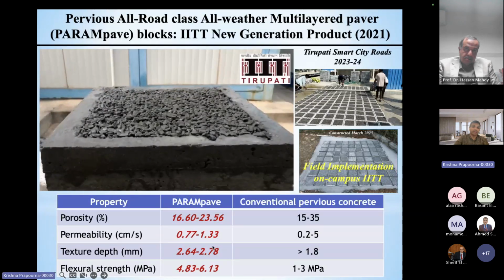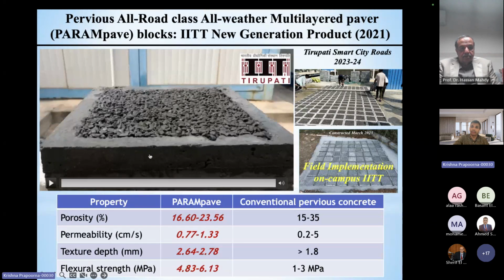The other advantage that we got here was the flexural strength increased by about 3-fold. Why is that? Because this pervious concrete doesn't have a concrete base. It's a regular pervious concrete. It's a slab 500 millimeter by 500 millimeter, or maybe 2.5 meter by 3.5 meter slab that you regularly construct. No, you don't want to do that. You want to create a pervious concrete block. That's called the Parampave. So we get a very good flexural strength, about 4 to 6 megapascal, beyond what the ACI, the American Concrete Institute, prescribes.